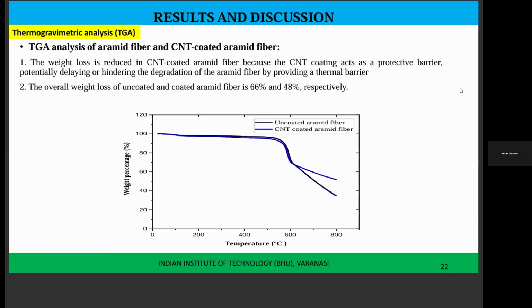Next slide, please. Once you arrange this, you can go for fabricating the composite, and then go for curing. After curing, you can get this polymer composite. TGA analysis, thermogravimetric analysis, looks at how the weight percentage changes as a function of temperature. We can say that this CNT coating acts as a protective barrier. It will delay or hinder the degradation of the aramid fiber by making a kind of thermal barrier. After 600 degrees centigrade, the uncoated one is decaying faster, but the coated one takes sufficient time. So weight reduction is less in the case of the coated one compared to the uncoated one.